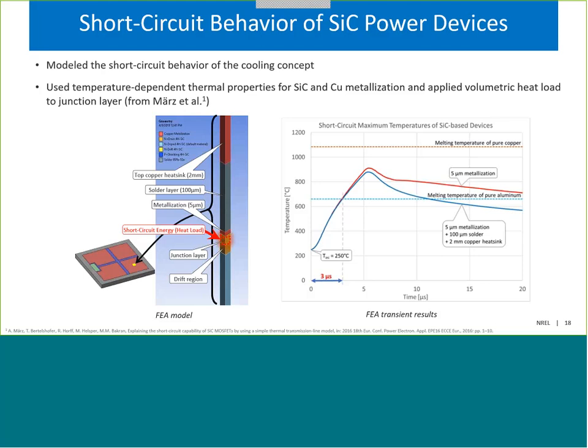And so the red line represents the performance for a conventional silicon carbide device with only a 5 micrometer metallization on the top side. So that's essentially the source pad metallization. And under the short circuit condition that we modeled here, this configuration had the highest temperature rise.